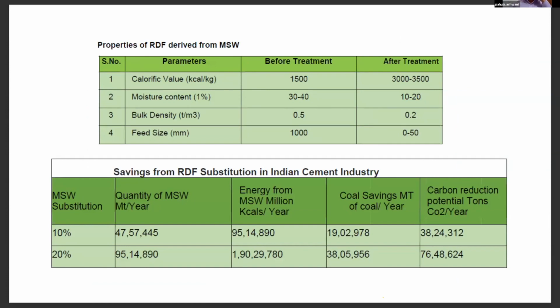Now, when we talk of RDF conversion derived from MSW, Indian MSW is not very good in quality as compared to European MSW, because of the difference in living standards of the Indian population compared to Europe. As a result, the MSW has a calorific value of 1500 kilocalories per kg or lower, which after treatment can be converted to around 3000 to 3500 kilocalories per kg in the RDF. Similarly, the moisture content is also very high. There is a lot of food waste in Indian MSW, because of which the biodegradables and food products are very high, and moisture content is also very high.